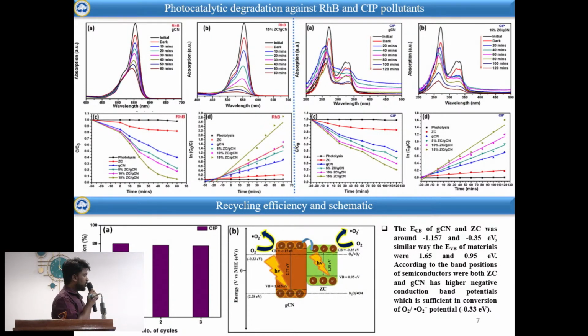So when we compared this data with pure graphitic carbon nitride and the composite sample, we can see that within 60 minutes we obtain the maximum degradation with the composite sample for RhB, and for CIP it has taken 120 minutes. The reaction rate has been calculated with respect to the pseudo first order reaction process. We have taken C by C naught as well as ln of C by C naught. Through this we can see that the 15% composite sample with graphitic carbon nitride has shown the highest slope, which enhances the rate of reaction faster within 60 and 120 minutes of degradation.